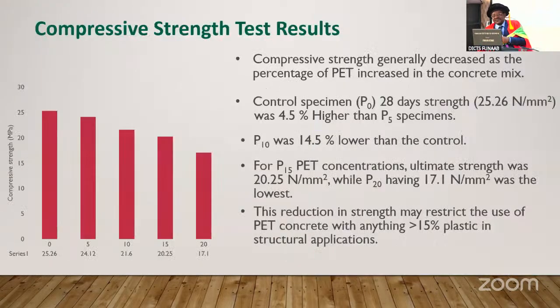Now, for the compressive strength, the compressive strength generally decreased as the percentage of PET increased in the concrete mix. The control sample at 28 days gave us 25.26 newtons per mm square, which was 4.5% higher than the P5 sample. P10 was 14.5% lower than the control. For the P15 PET concentration, the ultimate strength was 20.25, and the P20, which is the highest percentage, gave us 17.1 newtons per mm square, which is the lowest. This reduction in strength may restrict the use of PET concrete with anything greater than 15% plastic in structural application.